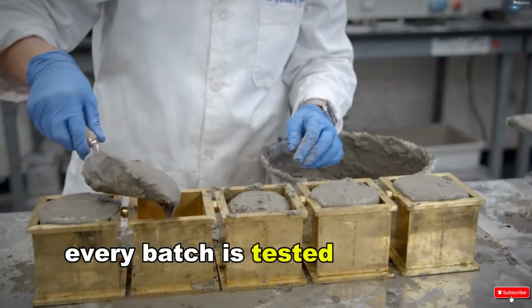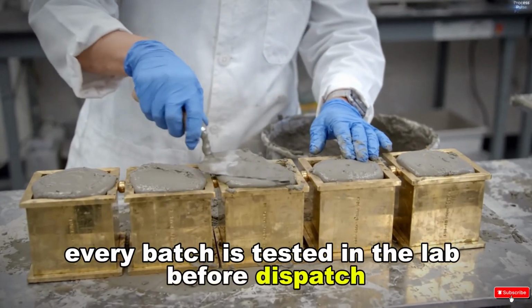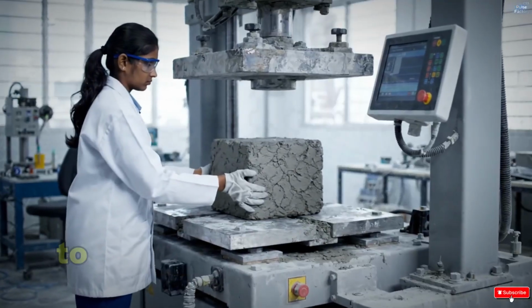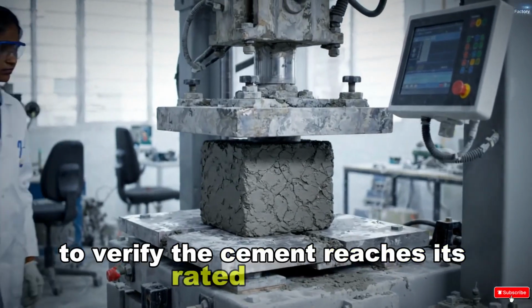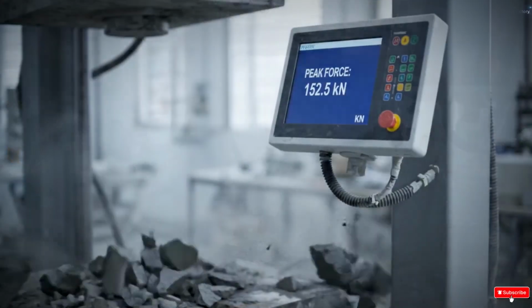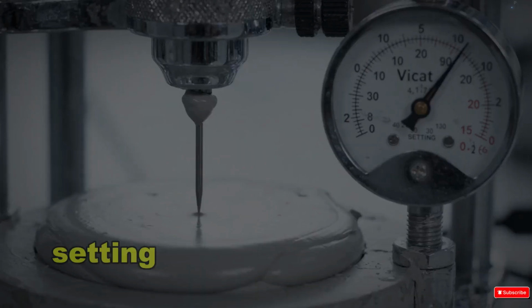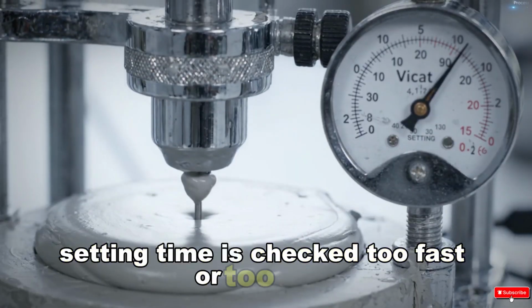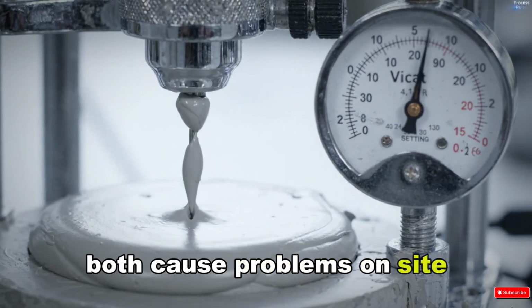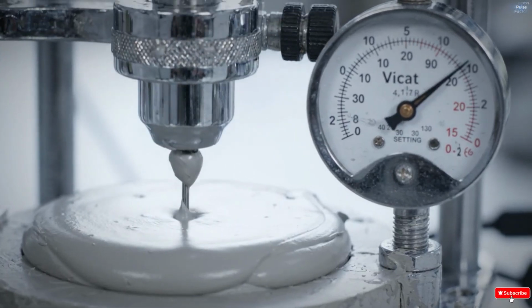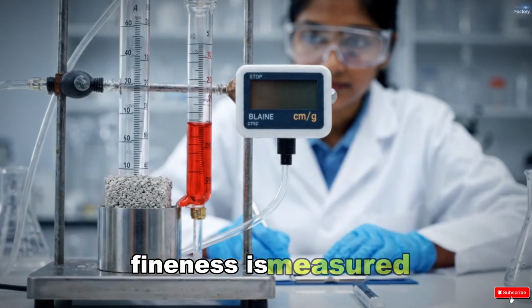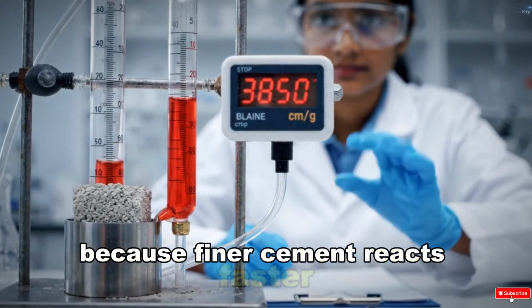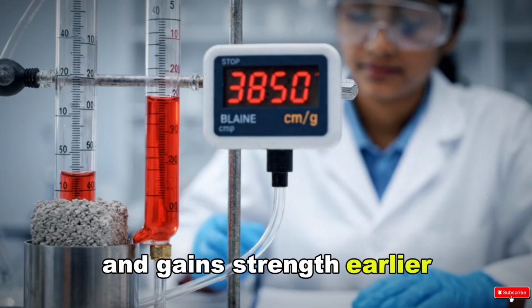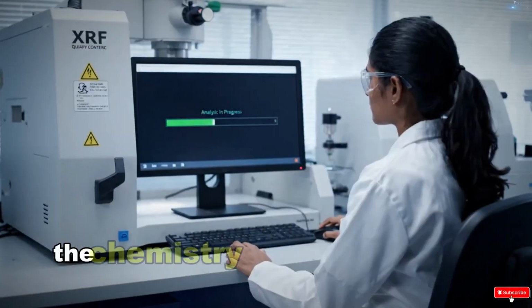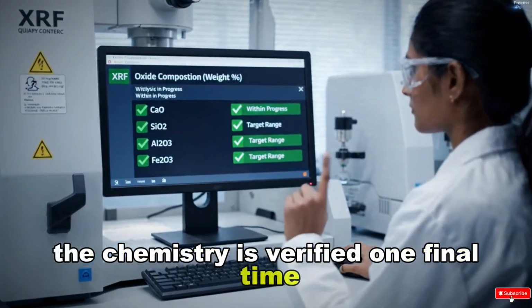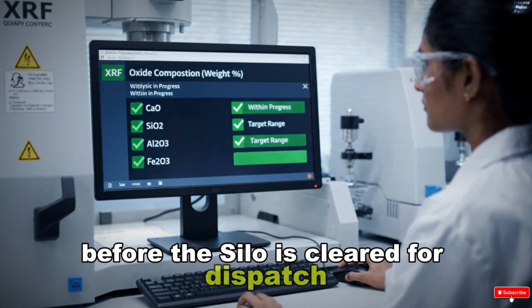Every batch is tested in the lab before dispatch. Cubes are crushed to verify the cement reaches its rated strength. Setting time is checked. Too fast or too slow both cause problems on site. Fineness is measured because finer cement reacts faster and gains strength earlier. The chemistry is verified one final time before the silo is cleared for dispatch.